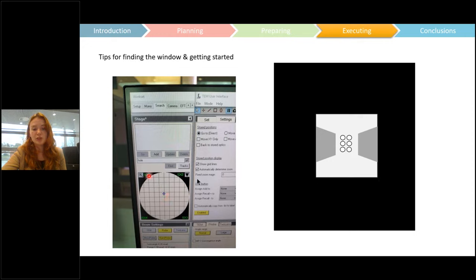then I would just use the search here on the left. Apparently there's also something similar in JEOL microscopes, to double click and move around until I find the window. Once I've done that, I'm actually somewhere on the window and I'm seeing something like here, or I then find a black edge and I follow around until I get to this, it's called the bow tie, I think, officially, until you get to this bow tie of grayed out area, which is thicker. I think it's the silicon carbide.